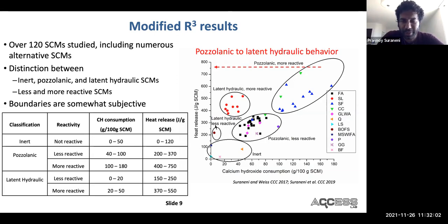Now, I have to point out that the boundaries are a little bit subjective. We basically got them from clustering of the various points. But really, is there a difference between a material that's here and a material that's here? That's debatable. We are working on improving these using algorithms, etc. But we have not yet come to that point. But essentially, it doesn't change the fact that somewhere about here is your inert limit. Everything above that is reactive. And if you have something that's on this side, then that's likely to be latent hydraulic.